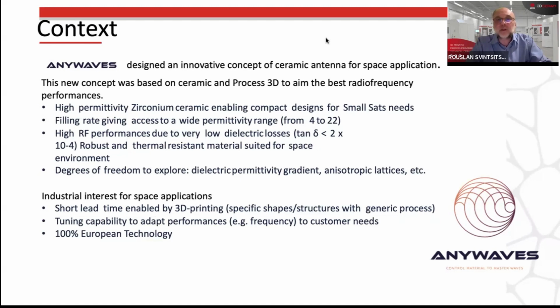And additive manufacturing was adopted because, first, it could ensure a short lead time to raise the maturity of the part, to test it, and to make it fly, and because of the tuning capability, because we can easily adapt. Again, we don't need any tooling. The tuning is just digital. So we can do, let's say, 2 or 3 different shapes of the same antenna in one print. And we can do it in a very flexible way. So if the antenna you printed doesn't work well, has to be enhanced, you don't need to change a tool. Just change the file and you reprint it again. So it's a matter of days, not months. And it was 100% European technology, which was very important for this company.